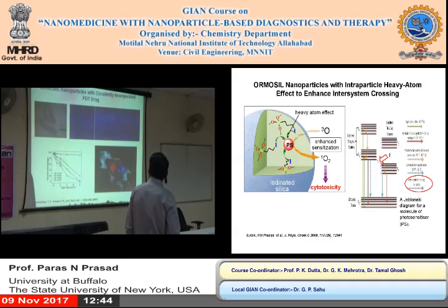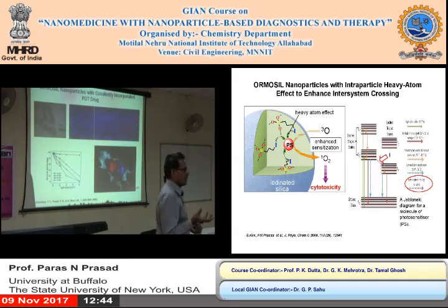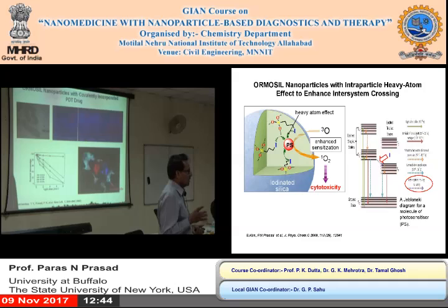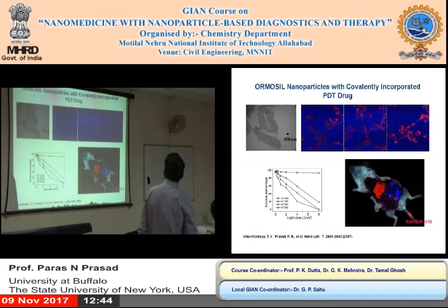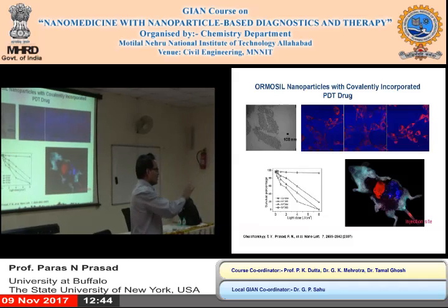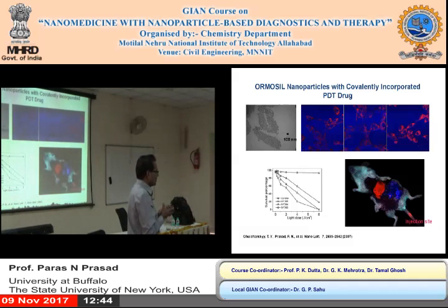Here we did the original work with this organically modified silica, where we can load the photosensitizer in many ways. This one was where we take the sensitizer covalently, by chemical bond. You can conjugate on the surface of the nanoparticle. Remember, when you make silica, a lot of OH groups are free on the surface. If they don't bond, through there you can connect chemically.